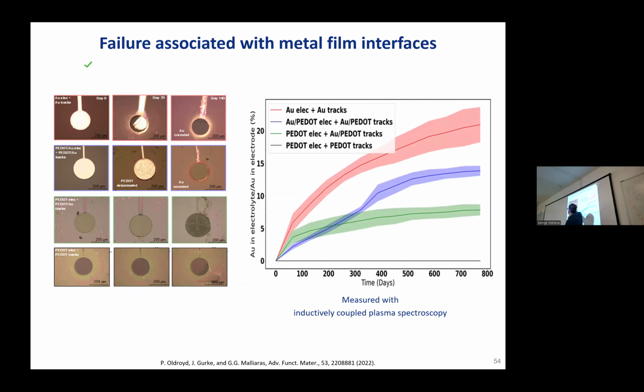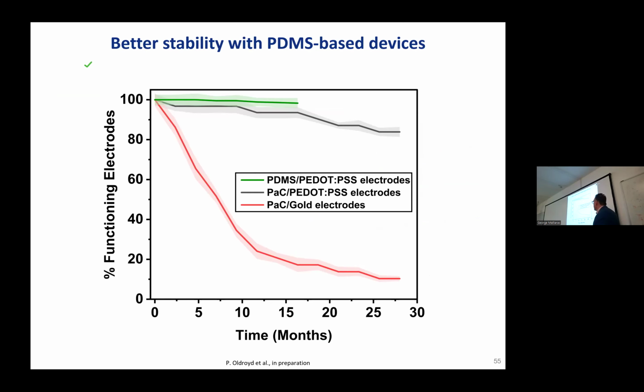So here you see the electrode has first delaminated, detached, and then the connection is also corroded. And we can measure the amount of material that is transferred from the electrode and all that, and try to understand failure modes. And through these efforts, we went from implants that fail within a year to implants that fail with an extrapolated time of 6 years, to implants that are very stable. These are still going on. I think this has over 10 years extrapolated lifetime.